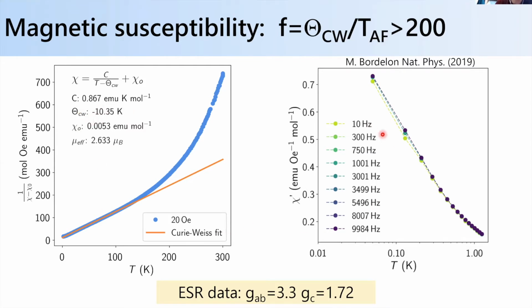And then we can look at lower temperatures, and this is AC susceptibility as a function of temperature. And the key is that you really don't see any features denoting any freezing or ordering in the system down to about 50 millikelvin. And the other key thing is that if we change the frequency of the AC probe, you don't really see any changes, which also helps to preclude any sort of unseen glassy freezing in the system, okay? And so, taking these 2 things together, we can ascribe what we call a frustration index to the system, which is a ratio of the mean field exchange that we're getting from the Curie-Weiss analysis divided by the lowest temperature that we've been able to measure the system.